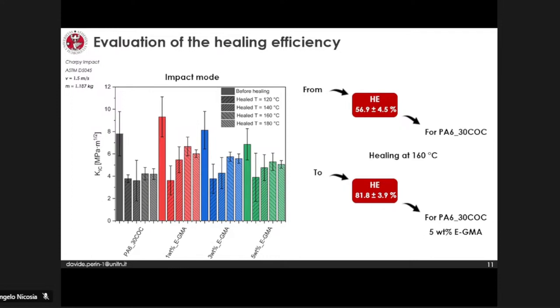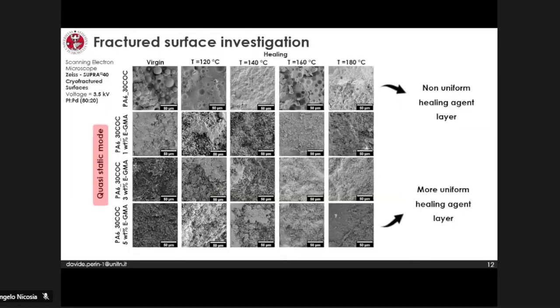To understand this, I performed fractography analysis, and here I reported the fractured surface before and after the healing process in quasi-static mode. It is possible to see that without the compatibilizer, we have a lack of adhesion between the domain of COC and the matrix of polyamide 6. By introducing the compatibilizer, the fracture morphology changed dramatically from brittle to severely plasticized.